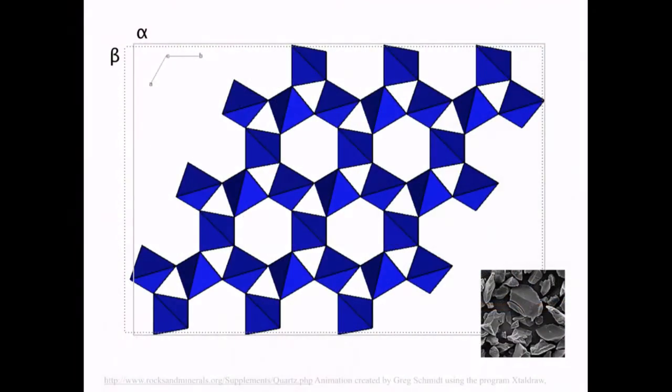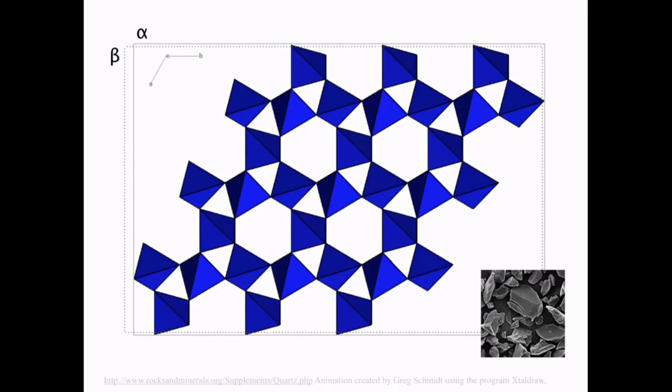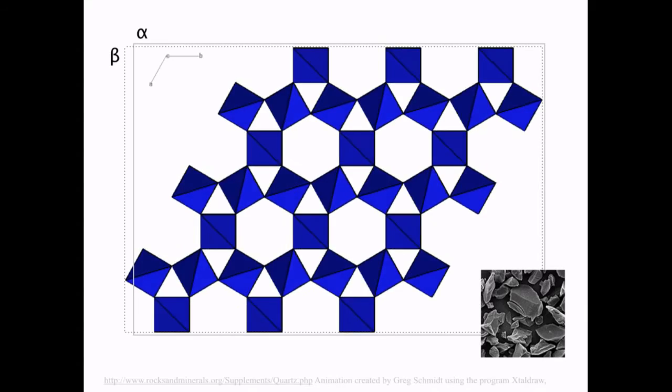So I found an animated GIF for this. So the alpha form is the one that happens at lower temperatures. And as you increase the temperatures, there's more motion in the atoms. And so a larger form that's more spread out is more favorable. And so that's the beta form. And so when you go through that point, it's going to occupy a larger volume. And so you want to be careful as you're heating up your ware that it doesn't go through that too quickly, so that it can evenly go through this transition instead of just the outside's already in the beta form and the inside's still in the alpha form.